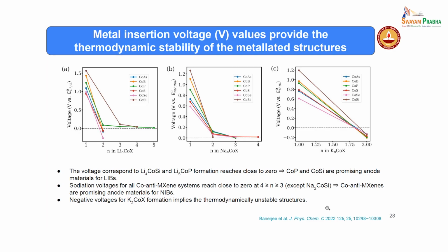So we wanted the average voltage to be as low as possible. Why? Because your cell voltage will be high only when the anode voltage is low. So here, if you are using potassium, the anode voltage is very high. So we are not supposed to consider these materials as anodes for potassium ion batteries. That's what it suggests. So these are the voltages corresponding to Li4CoSi, and these are reaching close to 0. That's the reason we are stopping. But you can see that you can absorb up to 4 or 5 layers on silicon and phosphorus. So for the lithium cases, these two anode materials can become very good materials. That's what it suggests.